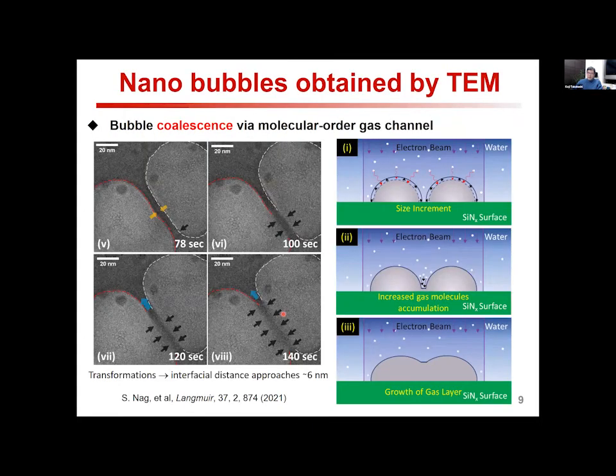For example, in our newest publication, we propose a new mechanism of nanobubble coalescence. As you see, and also as I showed here, these 2 bubbles are combined via this very thin gas layer. This is totally different from the macroscale coalescence of large bubbles, where the liquid film breaks down between them. But in nanoscale, this kind of very thin gas layer is very important. Anyway, this kind of understanding of nanoscale two-phase phenomena is very important for phase change heat transfer.